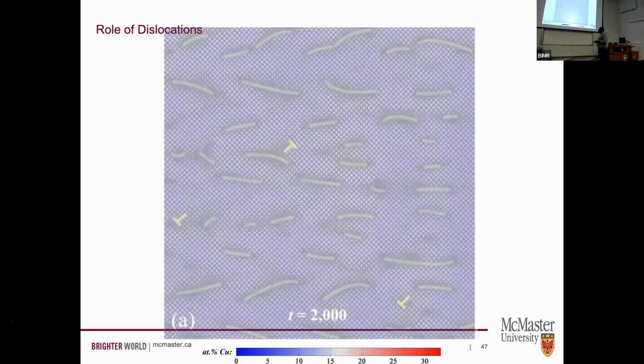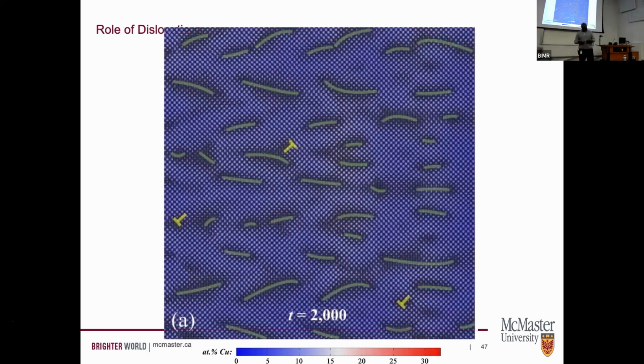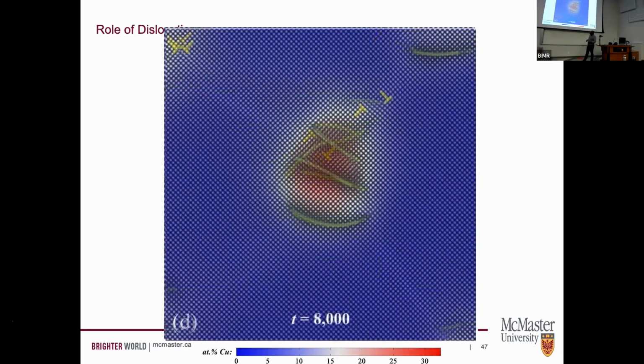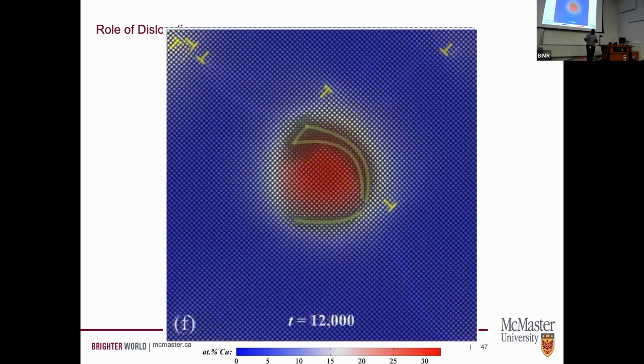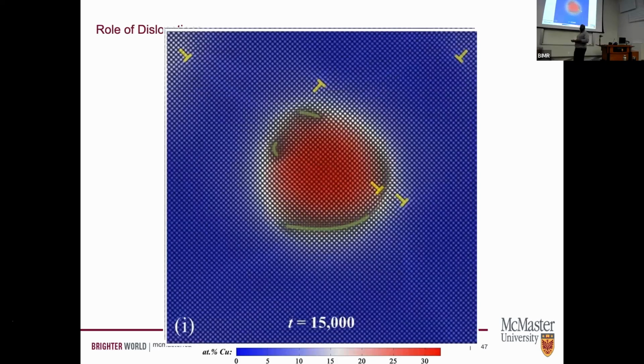So what's going on here? Well, first, let's take a look at exactly what the dislocations are doing. So what you see here is dislocations. The curves are dislocations that are on the surface and the crosses are in the plane. As the system evolves, the dislocations move around, the solute is attracted, and it turns out that everywhere you see one of these clusters of solute, it's dressed by dislocations. Okay? So dislocations are what are mediating this process.